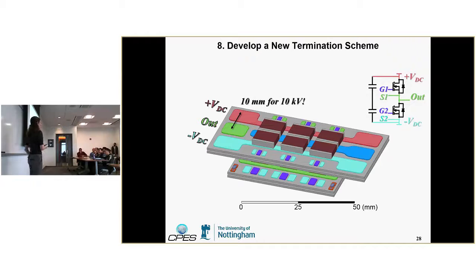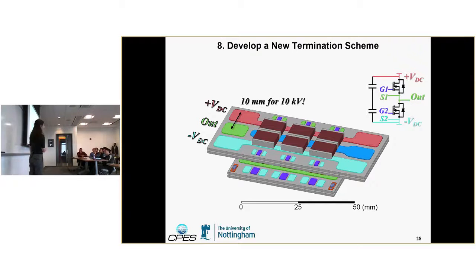So you've got 10 millimeters now for 10 kV. How do you terminate that? How do you connect that to the rest of your system? This is a huge issue. If you look at any high voltage connectors, the majority of power modules use bus bar connections. And when you get to higher voltages, you need to worry about creepage and clearance distances and standards. Those will significantly increase the size of your module. I think for 10 kV, it wants about 80 millimeters spacing. You can see the size of the power module is 50 millimeters. That's not possible. So we're looking at new termination schemes for that.